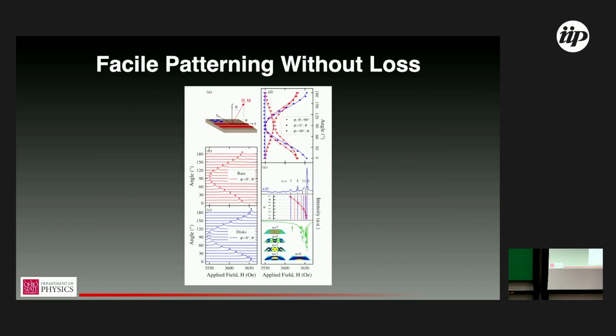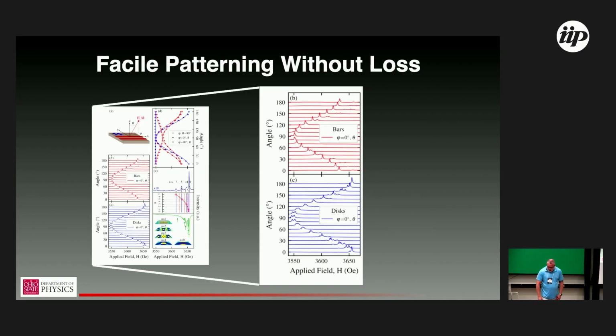This is something I showed on Monday as well, but just to refresh, this is now a characterization of two different arrays. In red, we have just bars. In blue, we have disks. That's kind of a dense plot, so I'll step through it a little bit. So this is rotating from in plane to out of plane, and you see the expected cosinusoidal variation from thin film anisotropy.